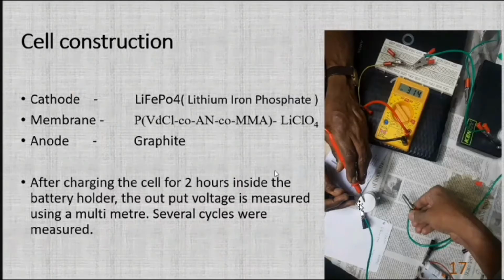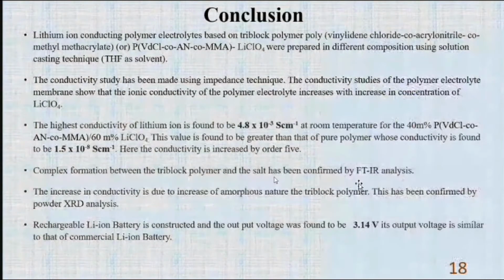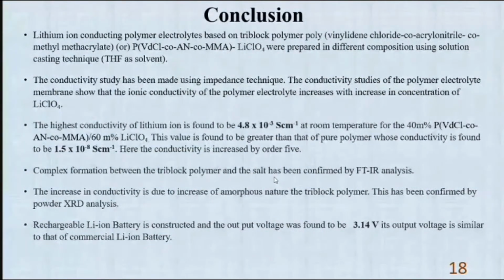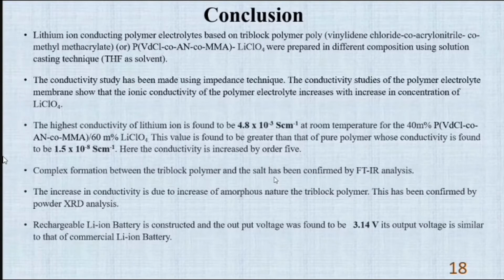Several cycles were measured, and the conclusion: the lithium ion conductivity of the pure polymer and the doped materials were studied. The highest conductivity is found to be of the order 4.8 into 10 power minus 3, which is increased by the order 5 from the pure membrane. The complex is confirmed by the FTIR analysis, and the rechargeable battery of 3.14 volts is similar to that of the lithium ion battery.